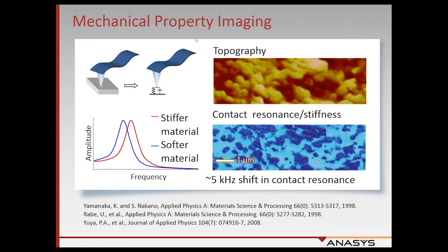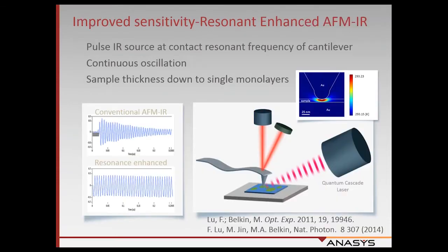Another capability we have is to do complementary mechanical property imaging, and basically what we can do is, in addition to measuring the oscillation amplitude, we can measure the oscillation frequency, and that frequency shifts depending on the elasticity of the sample. So we get a complementary measurement of topography, elasticity, and then also this chemical capabilities.